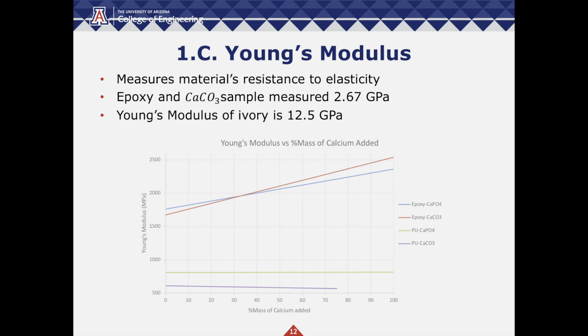Young's modulus measures the resistance of the material to stretching and deforming. It's a measure of elasticity. Our data showed that epoxy resin samples were better, and adding calcium increased the Young's modulus. The best sample was epoxy resin and calcium carbonate with a 1-to-1 mass ratio, which produced 2.67 gigapascals. Meanwhile, ivory's Young's modulus is 12.5 gigapascals.